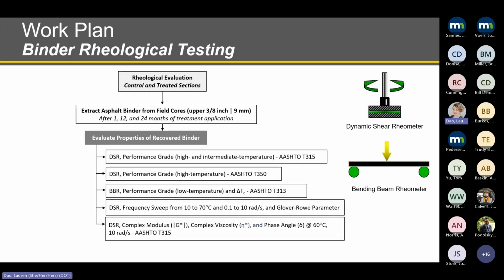For binder evaluation, we performed the tests that you can see listed here, basically DSR and BBR testing. As mentioned before, the current specification used for evaluating these products is the M332. On the M332, there are 3 major parameters that account for the binder rheological response. And to not only look into these 3 parameters, we add other tests for evaluation of the extracted binders.